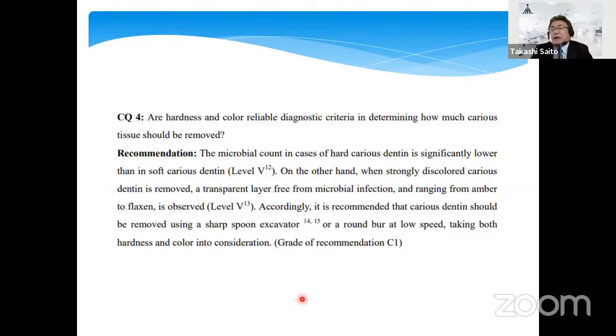To the question of whether hardness and color are reliable diagnostic criteria or not, they answer that the microbial count in hard carious dentin is significantly lower than in soft carious dentin. On the other hand, when strongly discolored carious dentin is removed, a transparent layer free from microbial infection, ranging from amber to flaxen, is observed. Accordingly, it is recommended that carious dentin should be removed using a sharp spoon excavator or round bur at low speed, taking both hardness and color into consideration. It is reported that a sharp spoon excavator can remove carious dentin having up to around 20 KHN, which is around the maximum hardness of infected dentin.